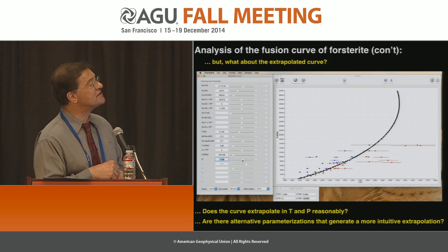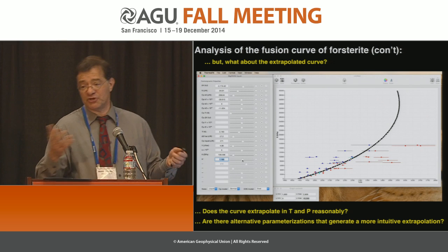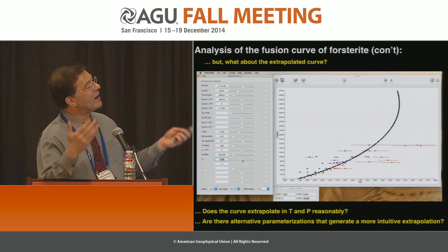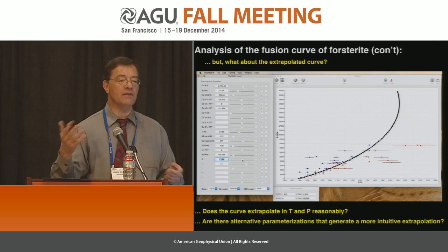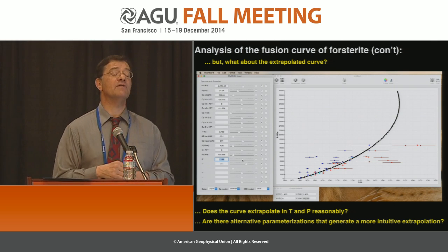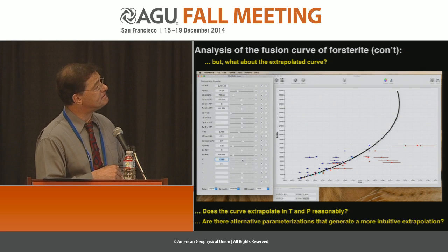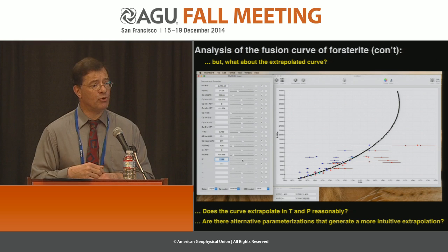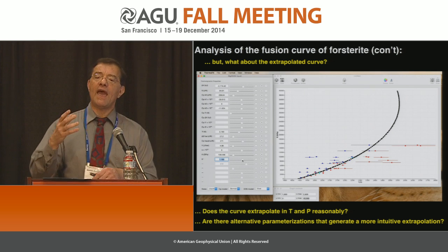I've just changed the derivative of the bulk modulus, which you would expect to be the most operative variable at high pressure, to a value where we can get a turnover in the density relations of the liquid and solid at high pressure. Now, of course, there's no data up there. So that's where we want to put it. But we may have an application.